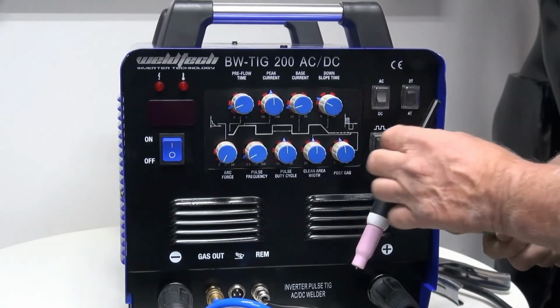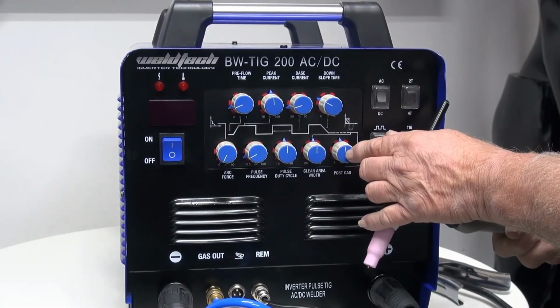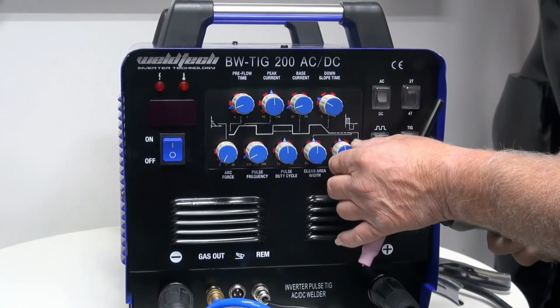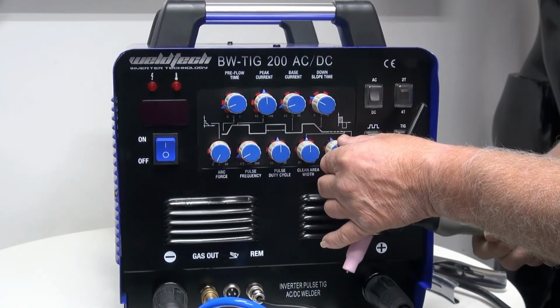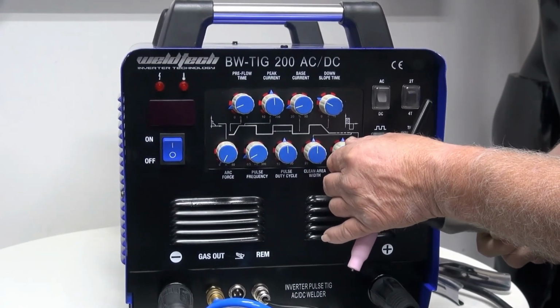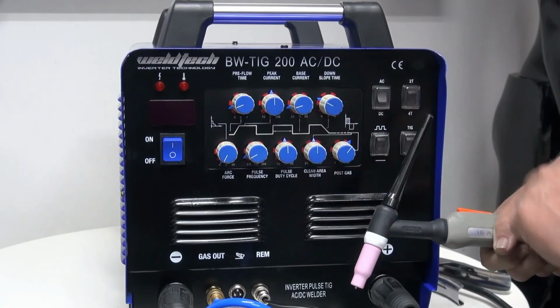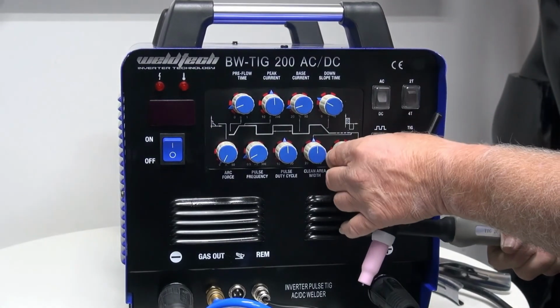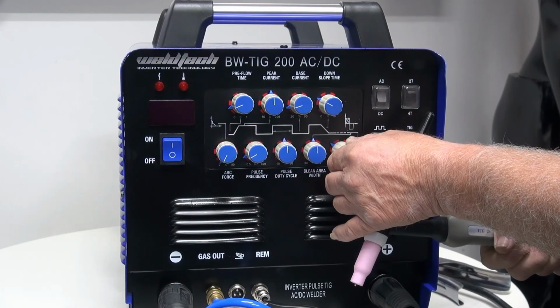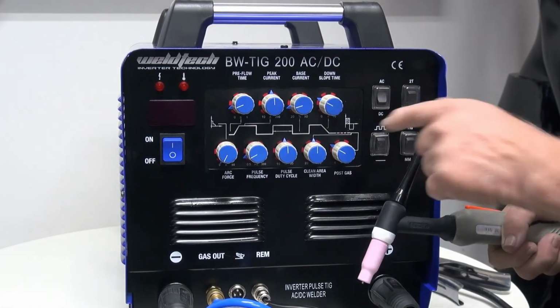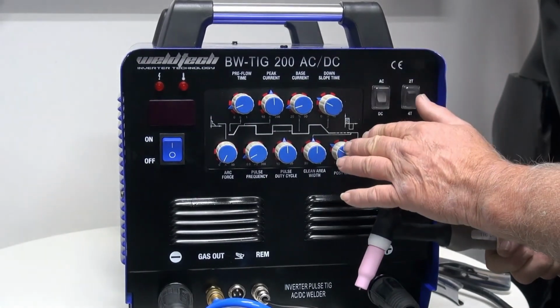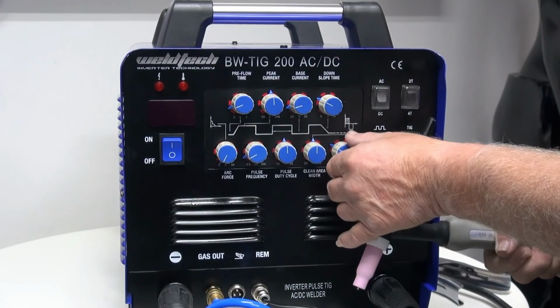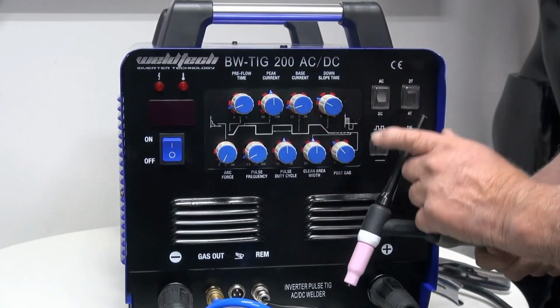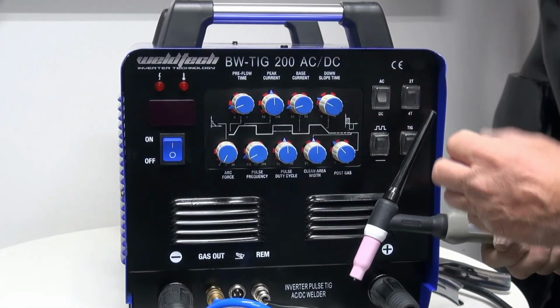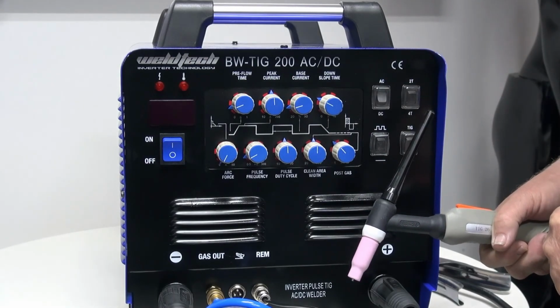Now, as a rule of thumb, you should have 1 second for every 10 amps. So you need to look at the amperage you're using. If you're using high amperage, the knob will be up around here. If you're using lower amperage, you can have the knob set down there. Don't forget it, set it properly. You're not wasting your gas if you use it properly. You're getting better starts, better tungsten life, and more protection at the finishing of your weld.